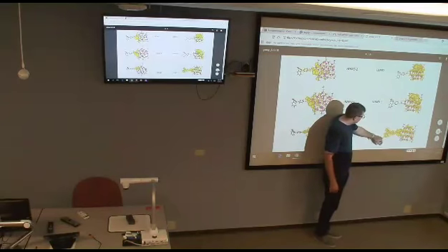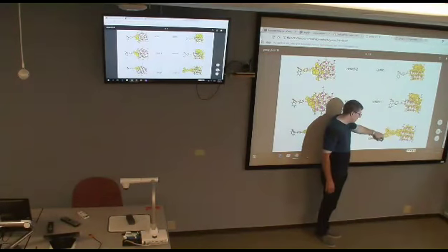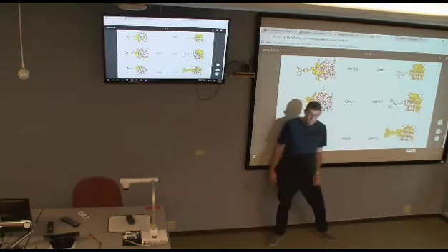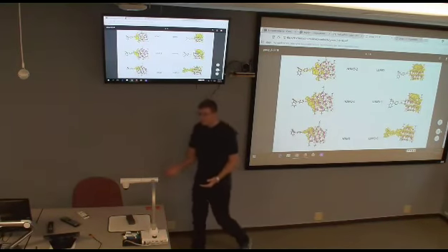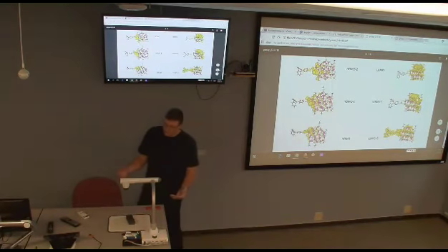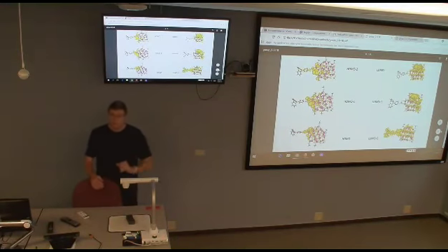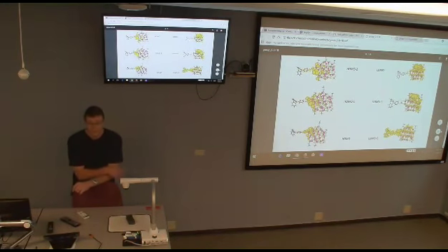You might get something like this every once in a while, like every third or fifth state. How that's going to influence dynamics, I would say, for excitation, it might really be a functional problem, right? And if that's the case, then going back and double checking with different types of functionals, TD-DFT and some of the Gaussian hybrid functionals, can correct that.